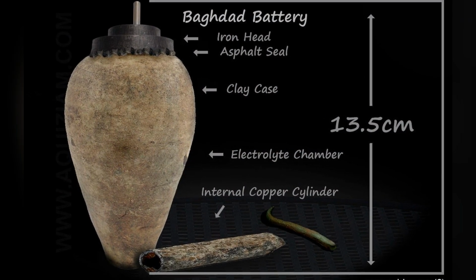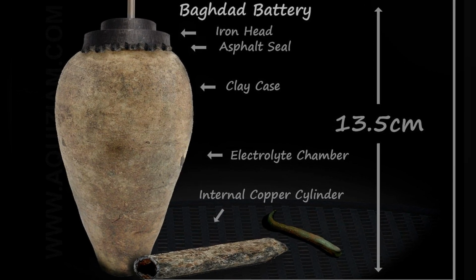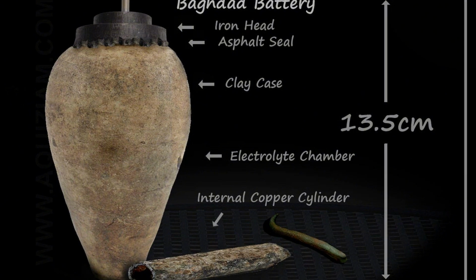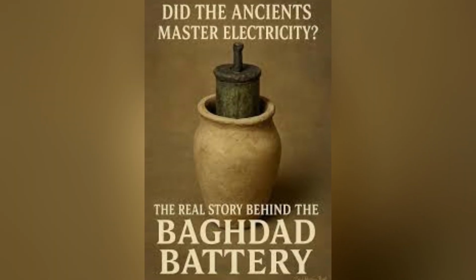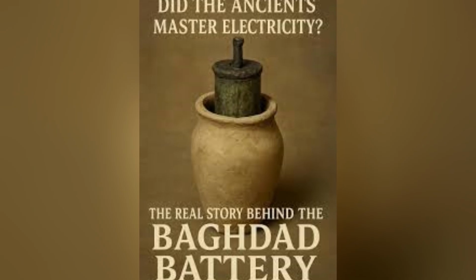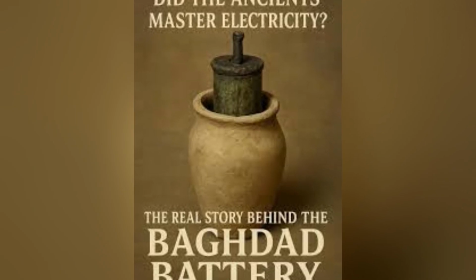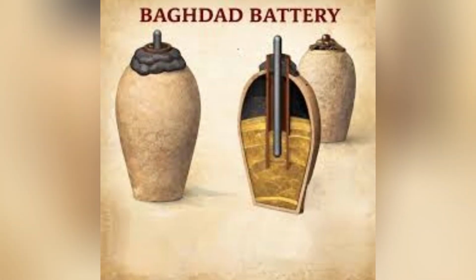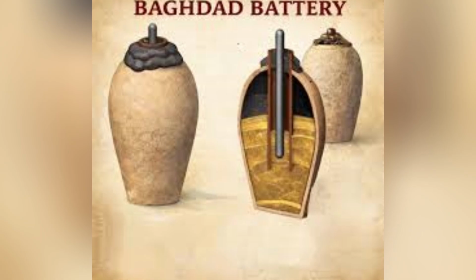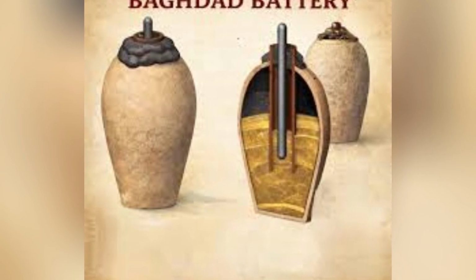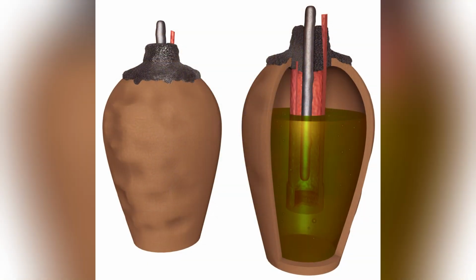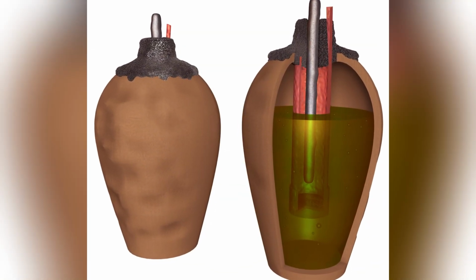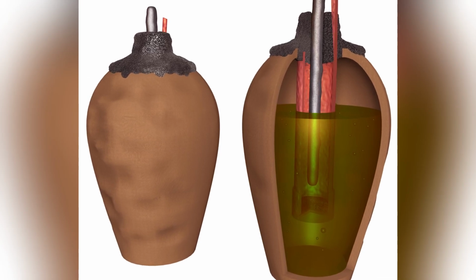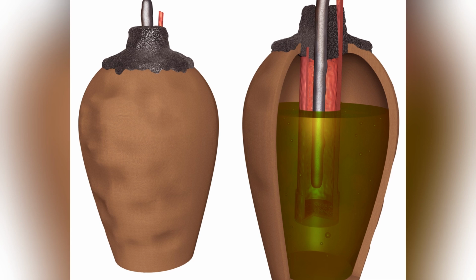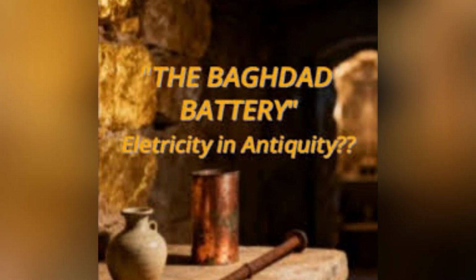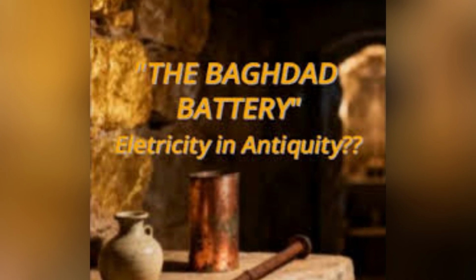The limited analyses that have been conducted on the corrosion products of the Baghdad battery's iron rod have not produced a definitive distinction between electrochemical and atmospheric corrosion, partly because the long period of burial, approximately 2,000 years, has obscured the original corrosion pattern, and partly because the analytical techniques that were used were not sophisticated enough to distinguish between the two types of corrosion. The application of more advanced analytical techniques, such as cross-sectional scanning electron microscopy and micro-Raman spectroscopy, to the corrosion products could potentially provide a more definitive answer, but the loss of the original artifacts during the looting of the Baghdad Museum has made such analysis impossible on the original objects.